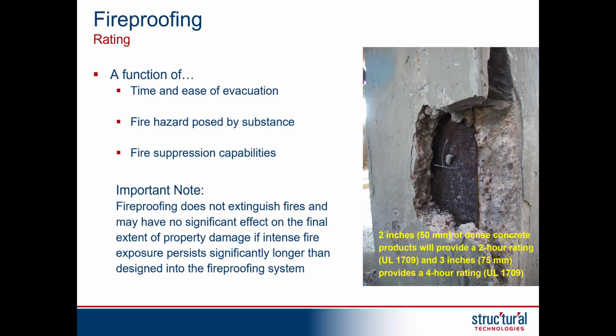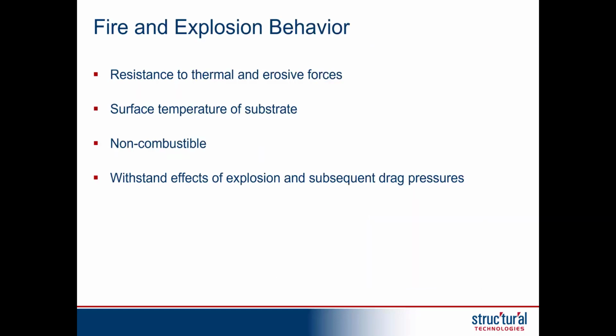And remember that these passive fireproofing materials, they don't extinguish the fire. And if the fire goes on longer than what they've been designed for, what will happen is you'll still get significant damage. And as you can see in the photo on the right, this is just showing some deteriorated, what we consider CUF, corrosion under fireproofing. That's a designation by NACE. 2 inches of dense concrete is going to provide about a 2-hour fire rating. 3 inches, 75 mm, is going to provide a 4-hour rating, and that's according to the American Petroleum Institute guideline, which is API 2218.